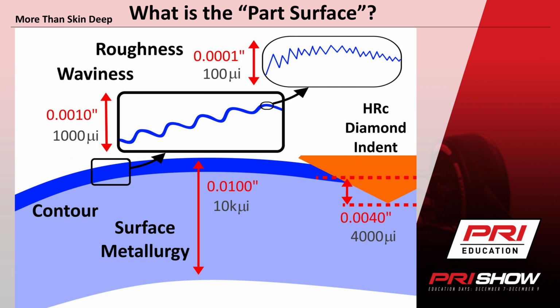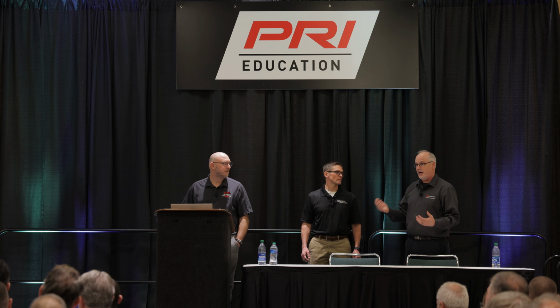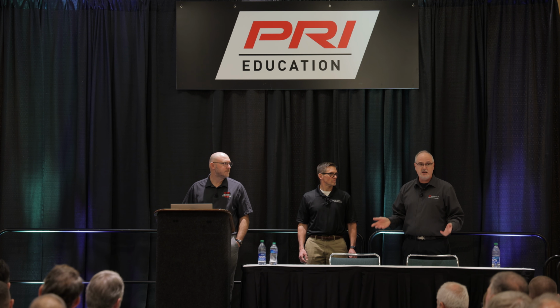Now what's amazing is when you look at HRC diamond indentation, when something's about 62 Rockwell, that only goes 3 thousandths deep after it preloads, so it's probably about 4 thousandths total. So you look at this as a 60 Rockwell, when you hit it, you've gone through almost all of your surface. It's kind of like trying to learn about the surface with the HRC gauge is like duck hunting with a 155 millimeter howitzer.